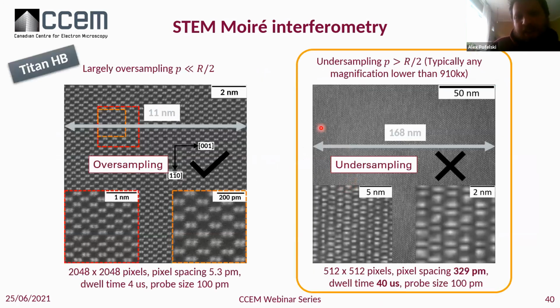If we relate to the previous part of the presentation, we have this largely oversampled STEM micrograph that we do in high resolution imaging. We said this was great, we can use it. And when it was undersampled, we couldn't use it, because the undersampling condition distorts the crystalline lattice, and we cannot recognize the silicon crystal structure, for example here, which is clearly the case. And that's the objective here. STEM moiré interferometry makes use of those undersampled micrographs to find the deformation inside. The transition is not direct though. There are some steps that need to be covered.